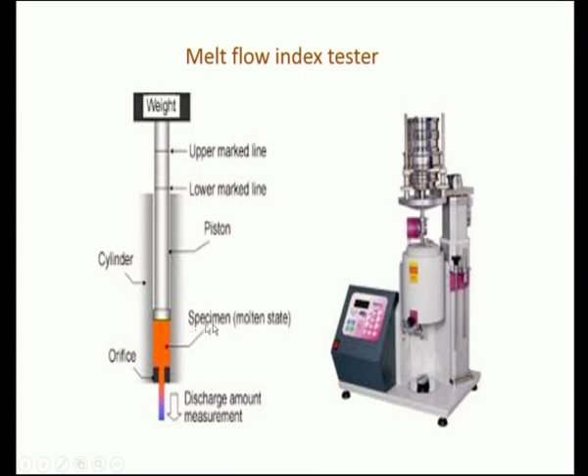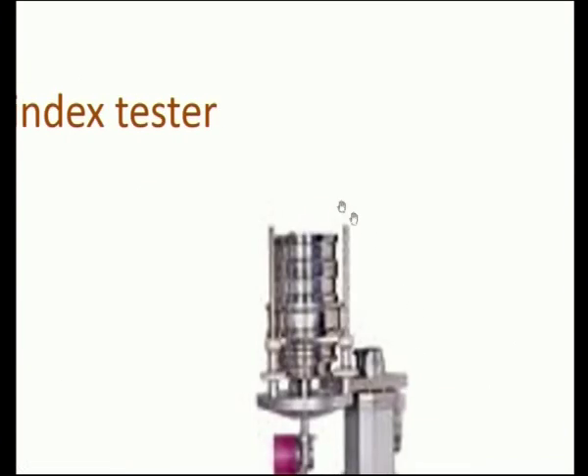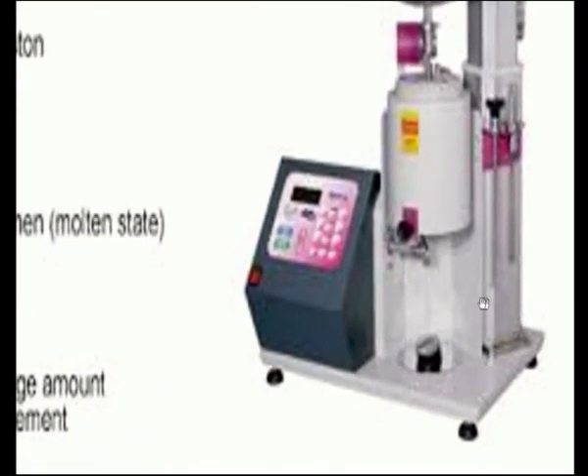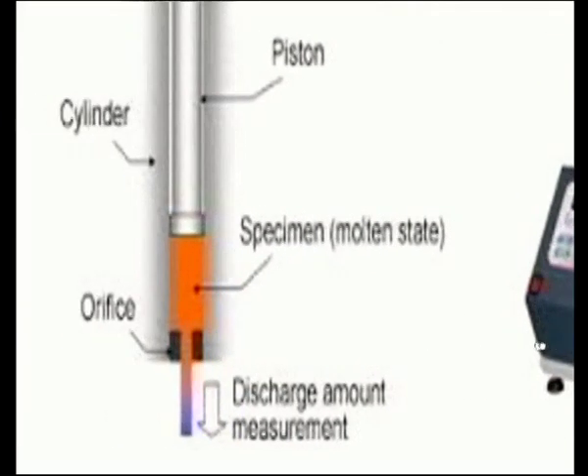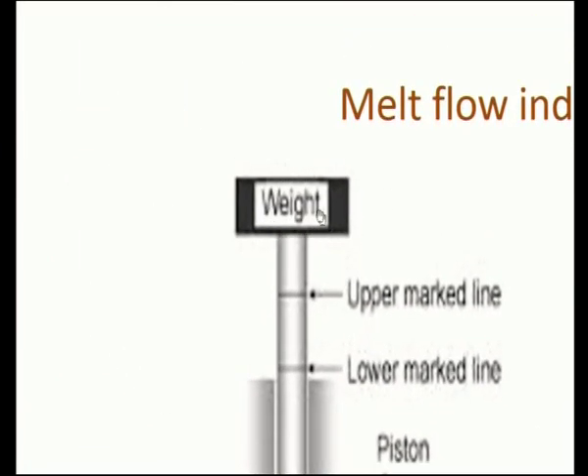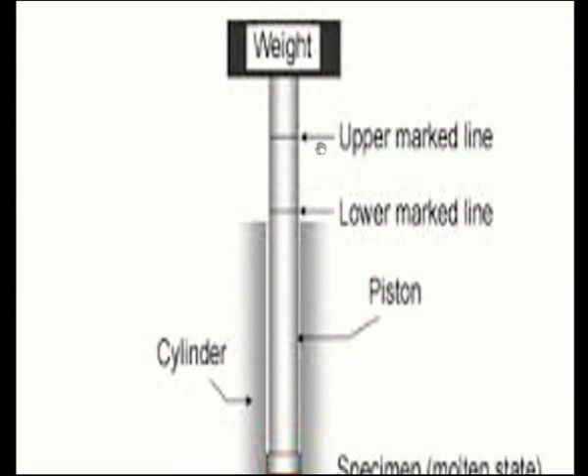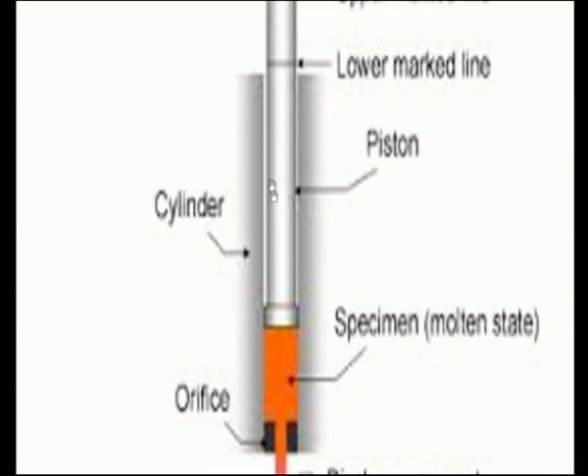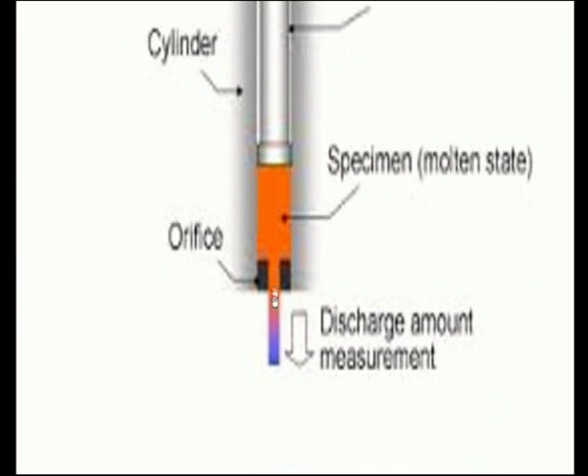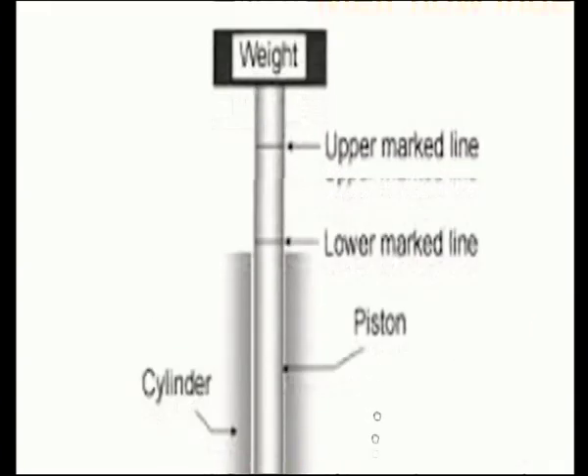This is a typical melt flow apparatus, where you have the orifice, a heating chamber, and the hopper. This is a typical melt flow instrument, with a display device which will directly display how many grams of material are extruded in 10 minutes. This is a block diagram. The weight is as per the ASTM standard, either 1 kg or 2 kg is applied, and then there is the piston movement from this point to this point, and this is the cylinder through which the polymeric resin will flow, and then this is the orifice. They will collect the polymeric resin extruded through this for 10 minutes, and then weigh it. For example, 10 grams in 10 minutes means the MFI value for that material is 10.